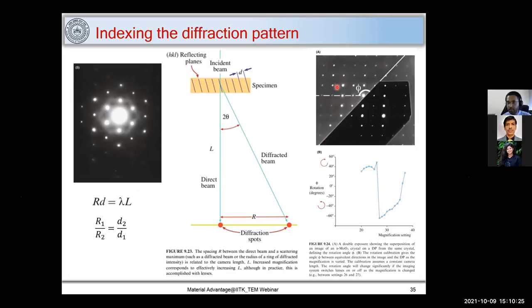the diffraction pattern will reorient or change. So there is a rotation when you go to a higher magnification, and you can correct that rotation based on the image. Here, this is molybdenum oxide, where I have shown this edge is the 001 plane, which bears some angle with this diffraction pattern. Based on this relation, you can find the rotation of this diffraction pattern with respect to the image plane.